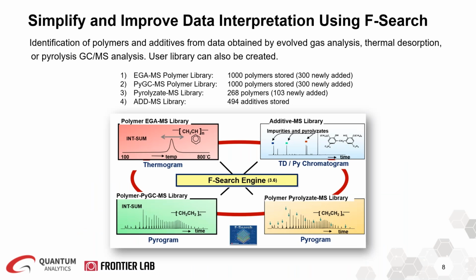So now let's talk about how we can analyze the results obtained from the pyrolysis GCMS. F-Search is a search engine with 4 unique libraries for identifying additives, volatiles, lighter components, as well as oligomers, heavier, and polymeric compounds. It is commonly used in conjunction with the MS library and allows you to also create your own user library to perform contamination analysis, comparison analysis, good versus bad, deformulation, as well as failure analysis. F-Search has other features like the ability to overlay different chromatograms. You can extract different m/z ions and integrated sum analysis, where the F-Search can actually integrate the whole chromatogram, make an average mass spectrum, and identify the corresponding compounds.